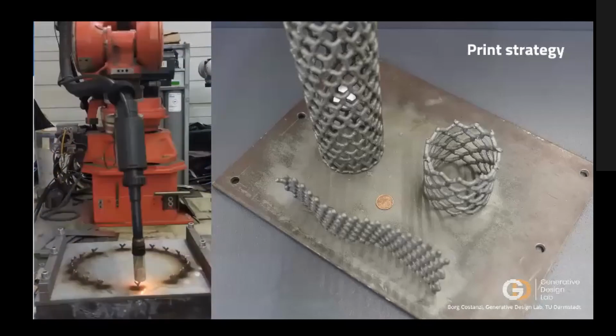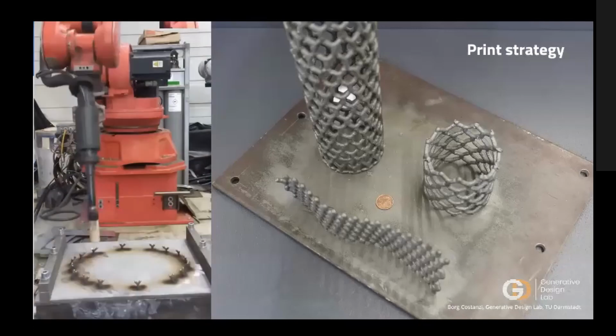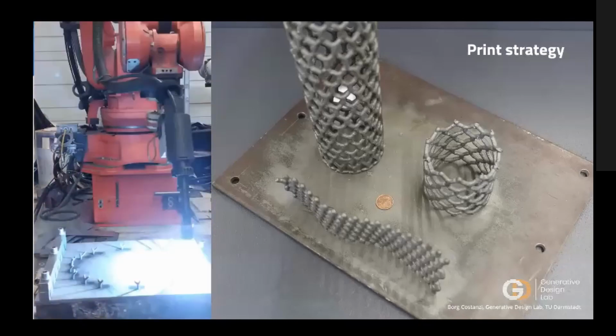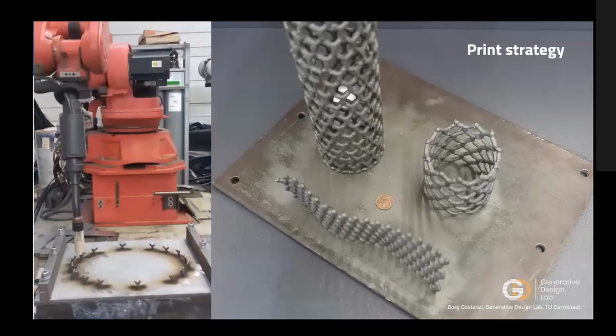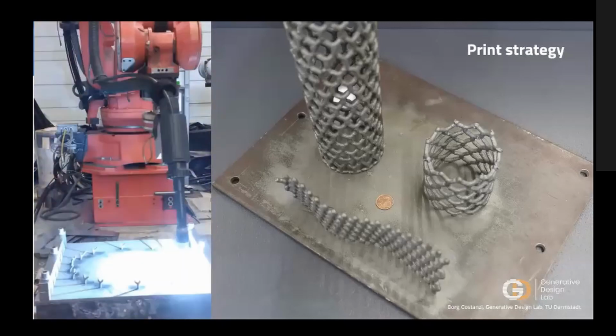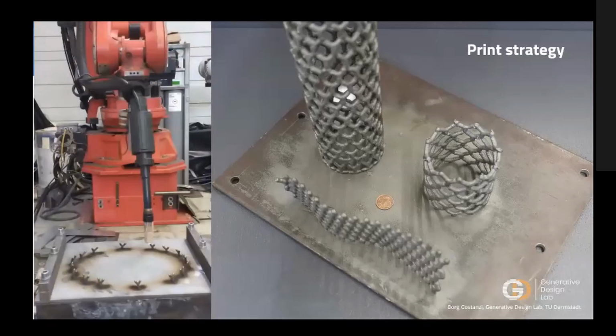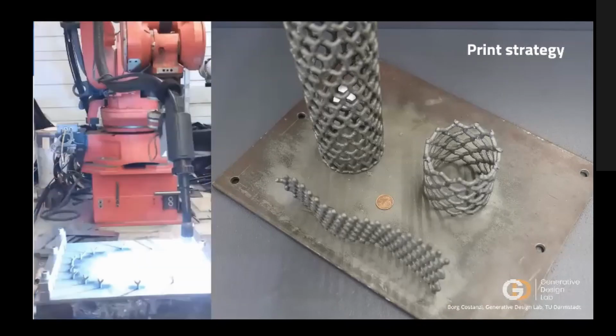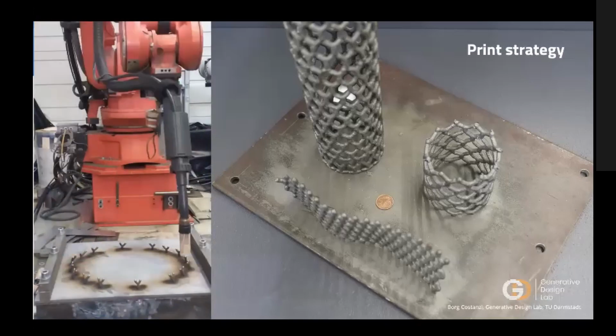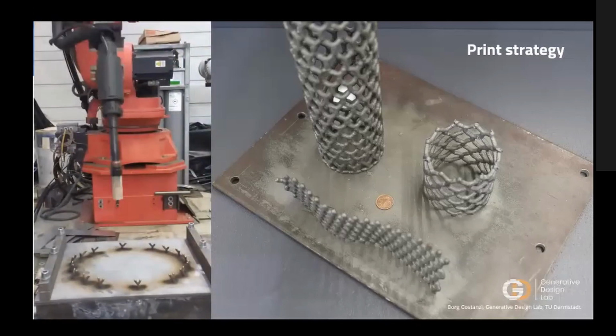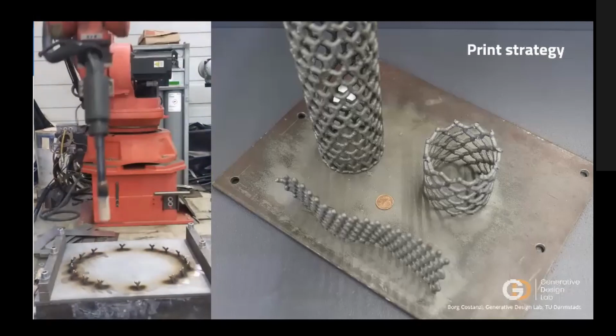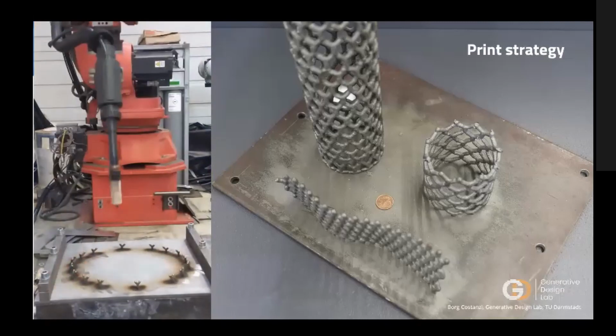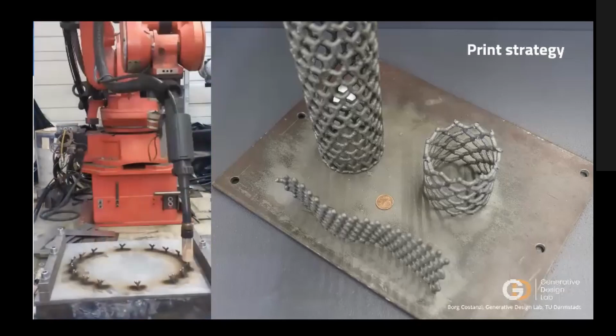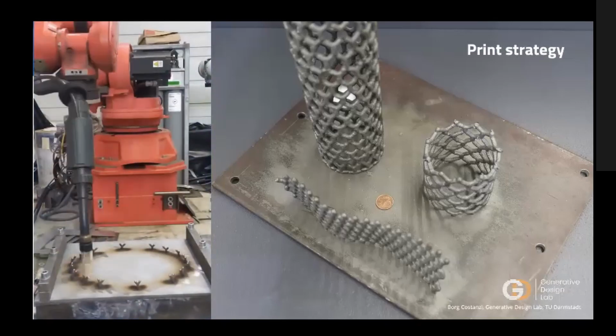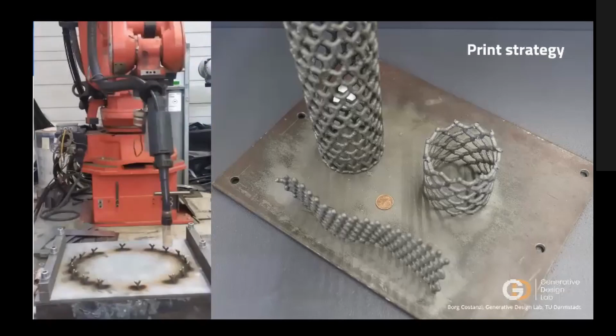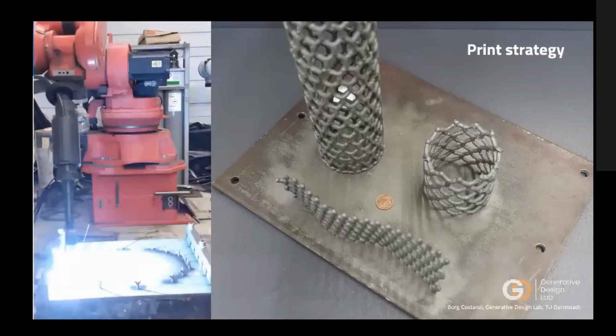And notice how we also go discontinuous in different points, and the printer jumps from point to point, and that's because of the thermal management. Again, that's very vital in 3D printing, in additive manufacturing, that we always have to optimize our process for the structural quality. And in wire additive manufacturing, the thermal management is one of the most important aspects that we have to consider to allow for enough heat to dissipate from the structure before we add the next printing point, to avoid thermal deformation and eigenstresses and so on.